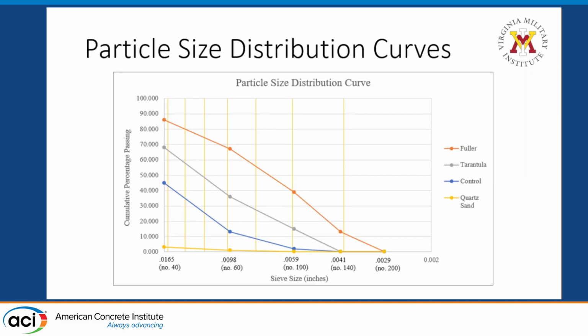This is the particle size distribution for each of the aggregates used in this project. The Fuller mix was essentially the finest gradation used, and the quartz mix, at the bottom in yellow here, was the largest. The last slide showed that the quartz mix was about 97% above the number 40 sieve. The quartz sand was just a bunch of big rocks, and the Fuller mix used a lot of the really fine aggregates that were found in the sand outside.